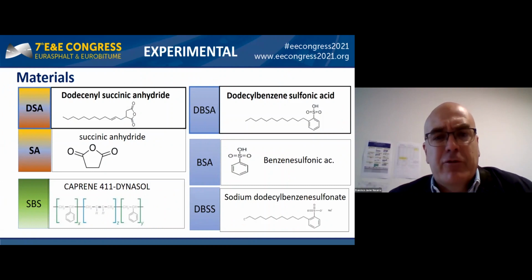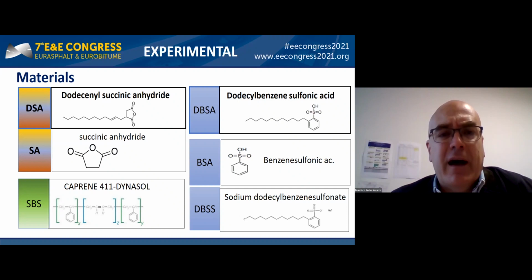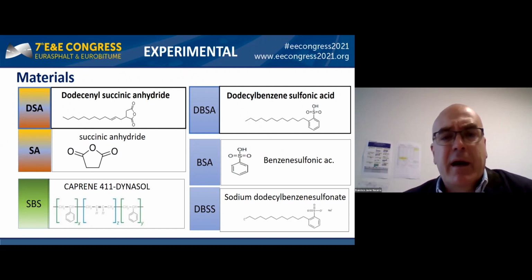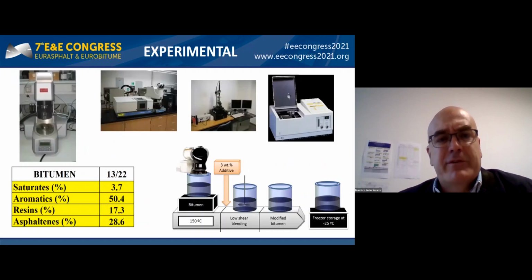Two different sets of surfactants have been used here, both of them having an aliphatic tail of 12 atoms of carbon: dodecenyl succinic anhydride, called DSA, and dodecyl benzene sulfonic acid, DBSA, and its sodium salt, sodium dodecyl benzene sulfonate. In addition, in order to study the effect of the polar reactive head, succinic anhydride and benzene sulfonic acid have also been used as bitumen modifiers. And finally, a typical SBS from Dynasol commonly used to modify bitumen has been used for the sake of comparison.